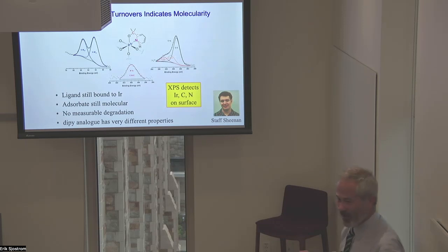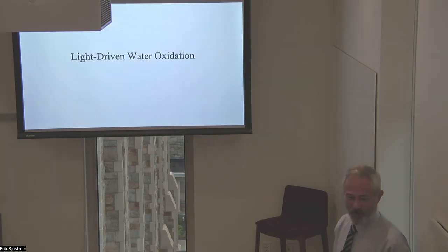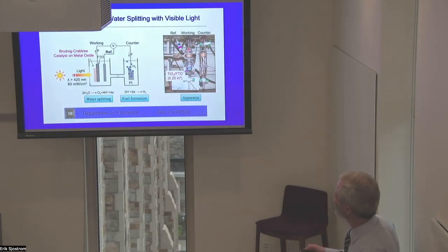So this is, I think, an illustration of what I said before. By heterogenizing these catalysts, you now overcome the problem of instability because they can't diffuse together and chew each other up. So can we do a light-driven water oxidation? I'll tell some old work with Brudvig just to illustrate this. What we'd like to do is put the catalyst on the surface of a metal oxide, shine light on it, and drive a water splitting reaction.